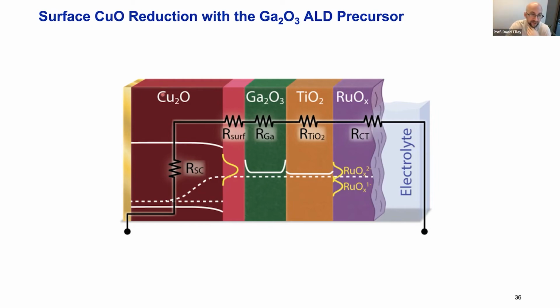And it turns out that the cuprous oxide here can thermodynamically react in the same way, but it turns out to be more kinetically stable. And so we think that with the high index facets, they either etch more efficiently, or they don't reoxidize as fast in that short time when we're going from the etching solution into our ALD reactor. So that's an interesting finding, which was not at all intuitive to me, at least, that there would be a dependence of the orientation on the performance of these films, since it's a highly symmetrical unit cell.